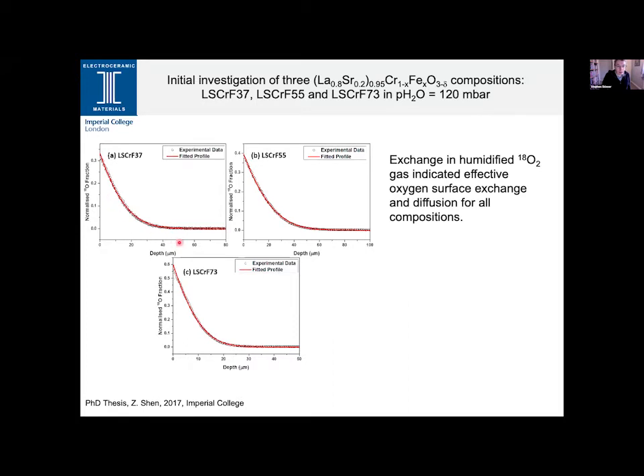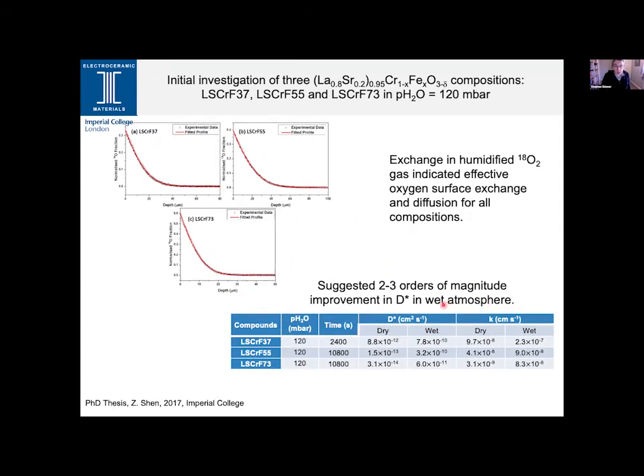From that, we can see we have some very nice diffusion profiles out to roughly 60 microns in depth. So we had effective gas exchange and effective diffusivity of the oxygen tracer in that scenario. From that, we then did some fitting. And rather surprisingly, what we found in this initial study was that for all three compositions, if we compared the diffusivity in a wet atmosphere with that obtained in the dry atmosphere, there was something approaching a 2 to 3 order of magnitude enhancement in the diffusion coefficient, whilst the surface exchange coefficients were staying roughly the same, not very much influence there at all.